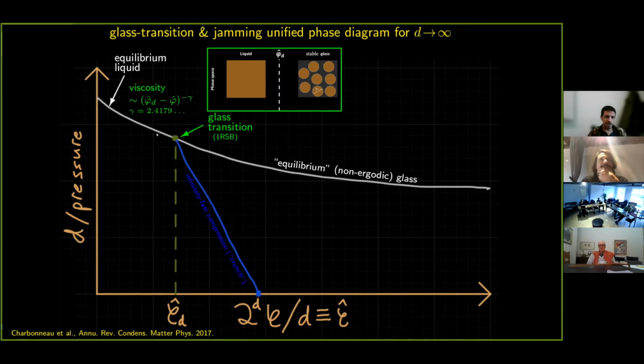Okay, if you start from the glass transition equilibrium state and make an infinitely fast compression of your system, then you arrive at some point here, which if you want is the random loose packing. It's the most dilute but jammed state that you can achieve with hard spheres. And this is the point where the pressure is singular, because the temperature in this